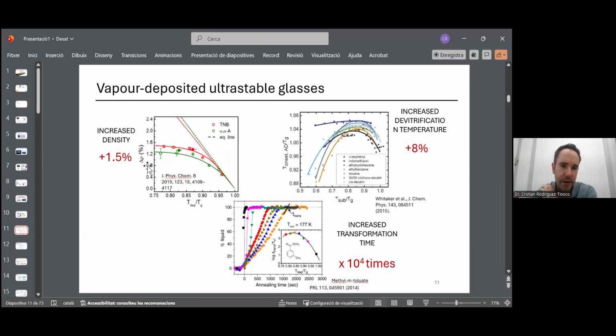Other properties which are also relevant in the field of ultrastable glasses are, for example, the density. This increased devitrification temperature is related to increased density. The molecules in the ultrastable glass are more efficiently packed, and therefore the density is higher, which at the same time is responsible for the increase in the devitrification temperature. You see here, we can reach maximum or approximately maximum densities when we grow the glass at 85% of the glass transition temperature.